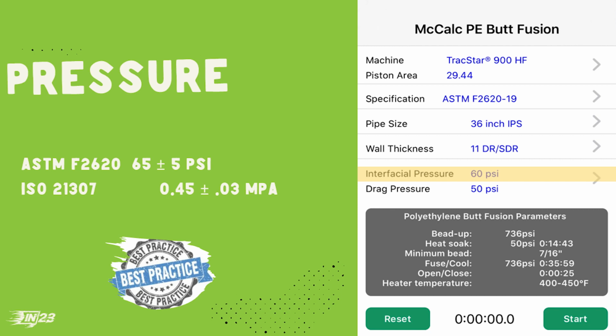We've seen that when we've had to drop our pressure because we're fusing a fitting on one side and it's slipping because the pressure is so high. Right. Pressure's so high, so we drop it down to 60, and then it drops below. So we've got to back out. And Mike, if you've got a significant amount of what you're calling chatter, for the rest of the room, if you're looking at a data logger graph, he's talking about up, down, up, down, up, down, up, down through the cool cycle.